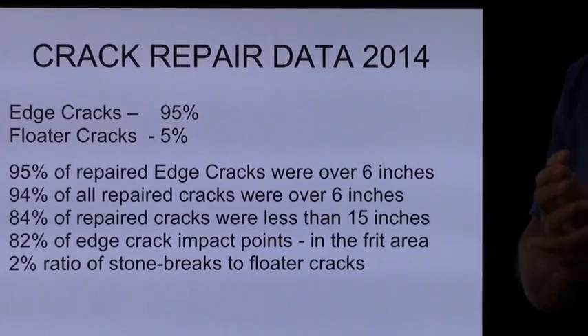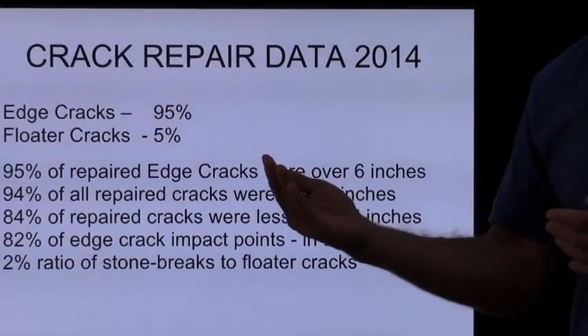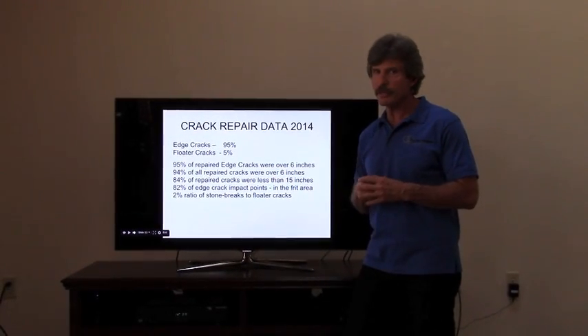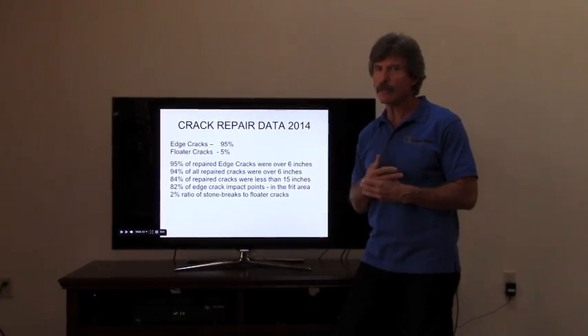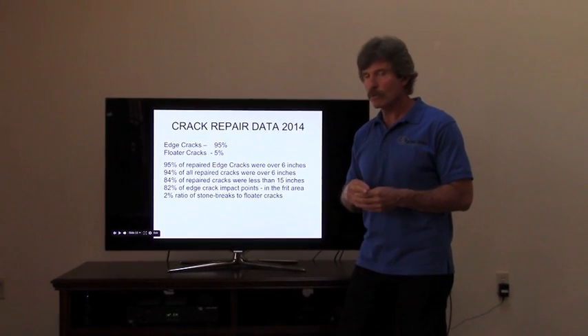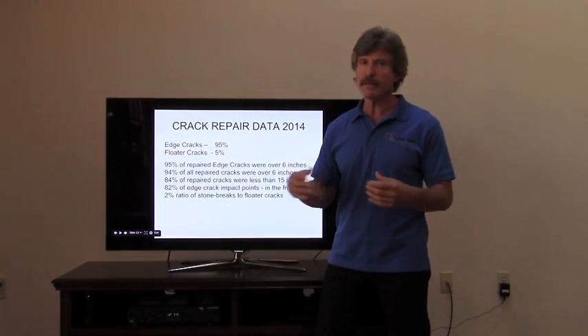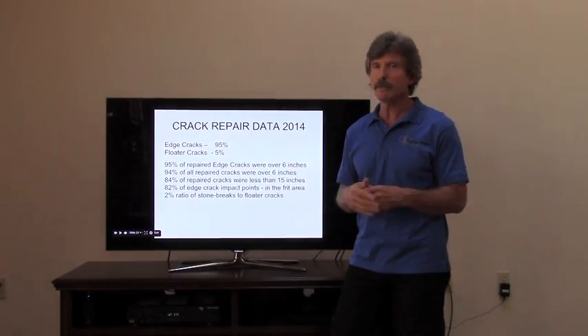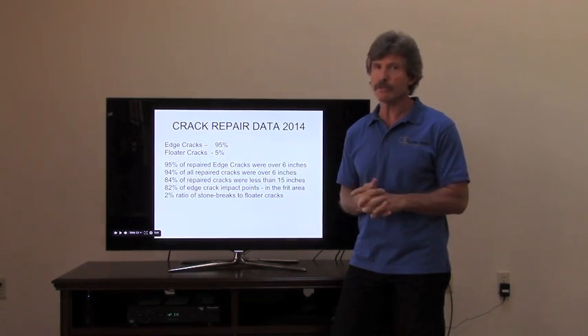Now, like I was talking about, the installation stress opening up the crack. Well, normally cracks under 14 inches haven't opened up wide enough to allow a lot of contaminant into it. Whereas once they get 2 foot long, 80% of them are contaminated, and even if you try to get the resin in there, they'll be full of dust.